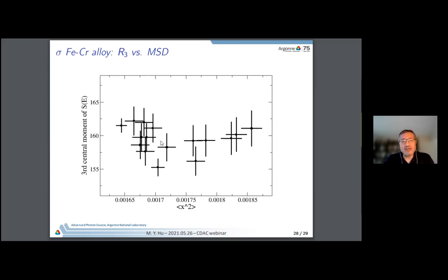So clearly, it tells you this is anharmonic, because in a harmonic situation, you would have a straight line, right? Because the force constant, the potential, doesn't change with the vibration or displacement. But now it does, and you see in the first part, the lower temperature part, actually the B term, the linear term, is negative. Negative means in the potential you have a negative quartic term. The quartic term is kind of large, right?